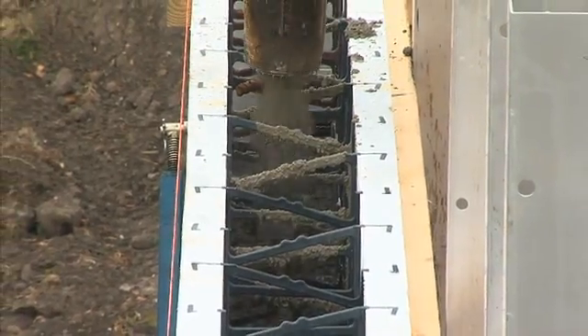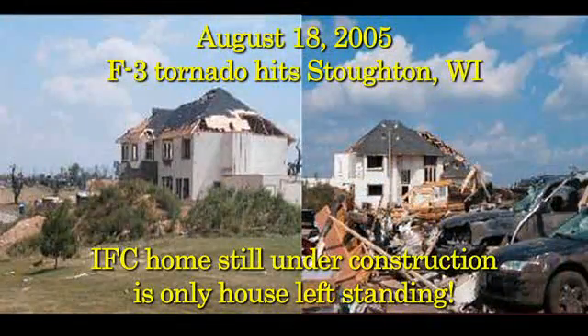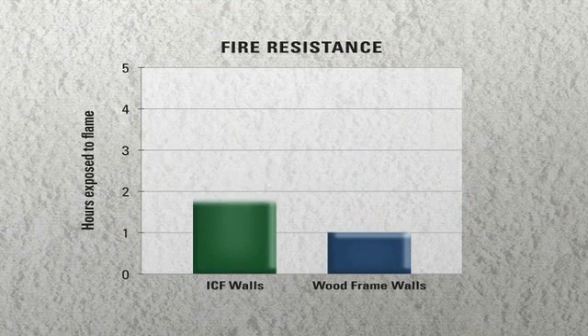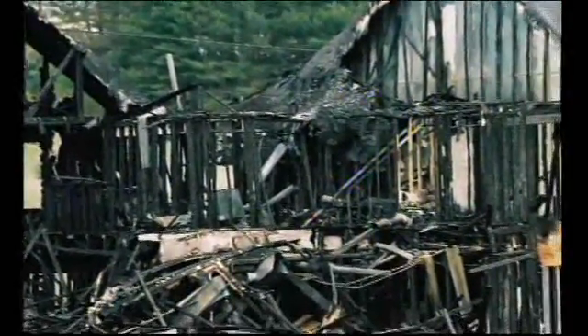The high mass walls of an ICF home not only give it a remarkably solid feel, but they also make it safer for the family and a solid, secure investment. Concrete homes have a proven track record of withstanding the ravages of hurricanes, tornadoes and fires when all the stick-built houses around them are in ruins. In firewall tests, ICFs stood exposure to intense flame without structural failure longer than common frame walls. ICF walls did not allow flames to pass directly through, nor did they allow enough heat through to start a fire on the cool side for two to four hours. In contrast, wood frame walls typically allow both flame and fire-starting heat through in an hour or less. Many insurance companies are now offering a discount on homeowner's policies for an ICF home.